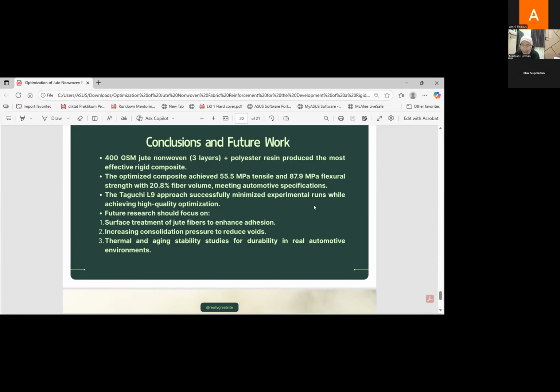And this paper explains that the Taguchi L9 approach successfully minimized experimental runs while achieving high quality optimization. For future research, we should focus on surface treatment of the jute fiber to enhance adhesion, increasing consolidation pressure to reduce voids, and lastly, thermal and aging stability study for durability in the real automotive